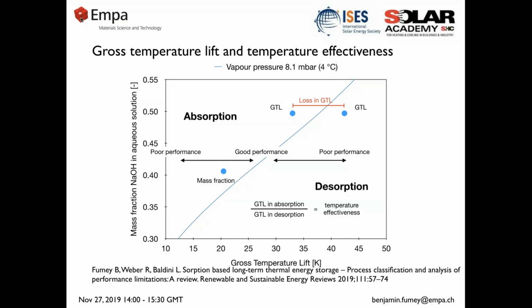And the blue line is the vapor pressure line here in our case at an evaporating temperature of 4 degrees, and absorption is always going to be above the line and desorption is going to be below the line. And very important for heat storage here is we want to be able to perform close to this equilibrium line. And you also see that in this desorption, the practical gross temperature lift is always going to be slightly greater than equilibrium. In the absorption, it's going to be less, and here we already can point to a loss in the gross temperature lift, or if we define it as the temperature effectiveness, would be the gross temperature lift in absorption divided by gross temperature lift in desorption. This is also further alluded to in the below mentioned publication.